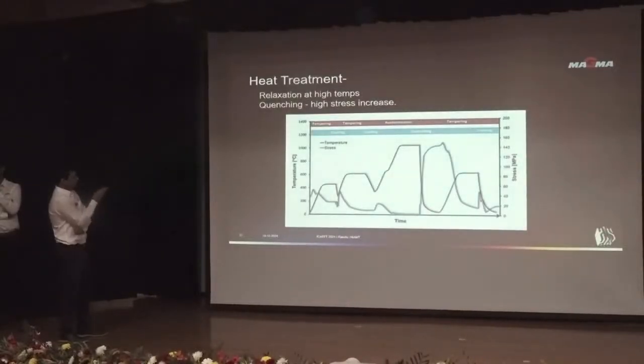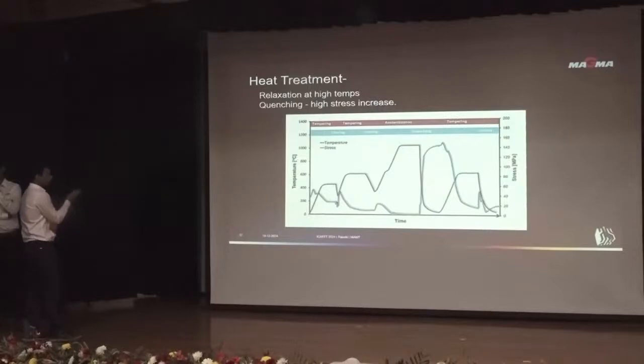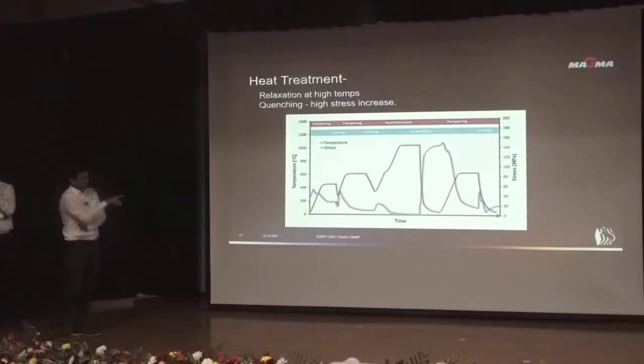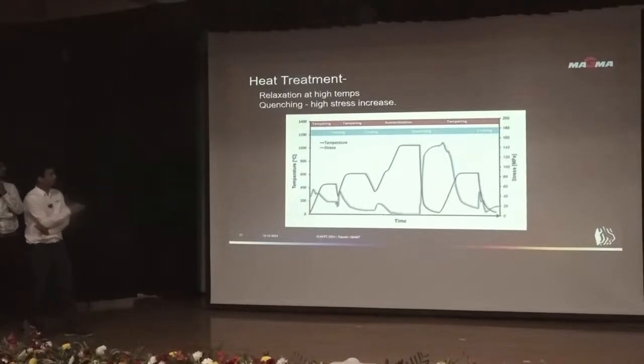What we found is that during heat treatment, the relaxation at high temperature was very good in the core areas or thick areas of the casting. During quenching, high stresses increased, but they were acceptable at the end of the cycle. It was only around 20 MPa, so that was acceptable in thick sections also.